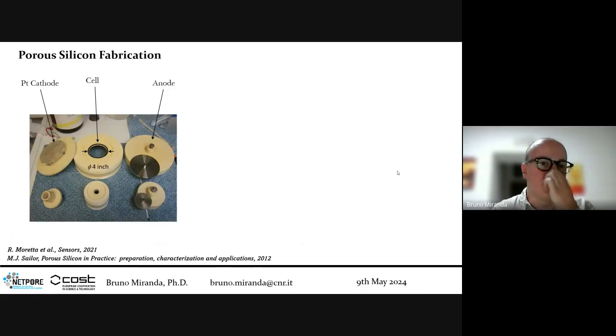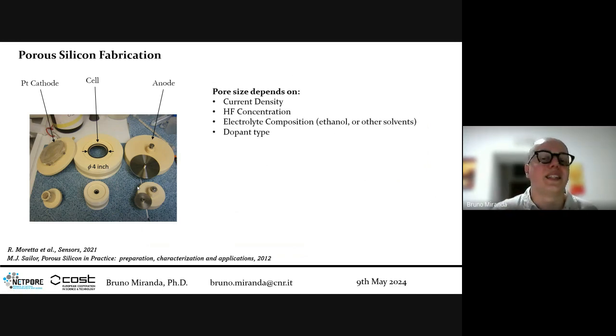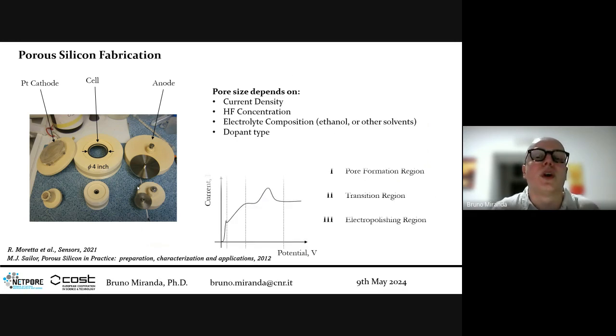How is the cell made? These are two different types of cells we have in our lab. We have the cell in which we put the silicon wafer entirely, or a piece of it. We have the platinum cathode and the anode, and we close this chamber. According to the current density, the concentration of electrolyte, the hydrofluoric acid, and the electrolyte composition—which can be made with ethanol or other solvents—but also the doping, we can have different curves.